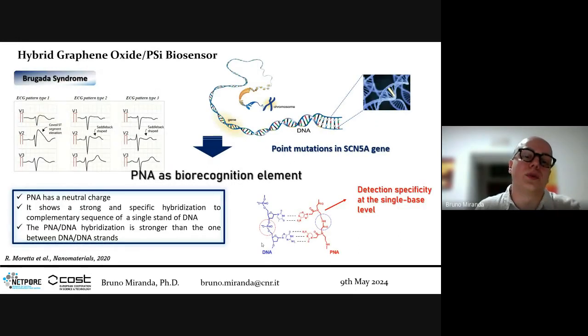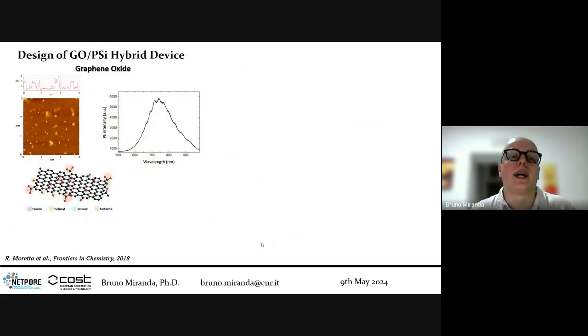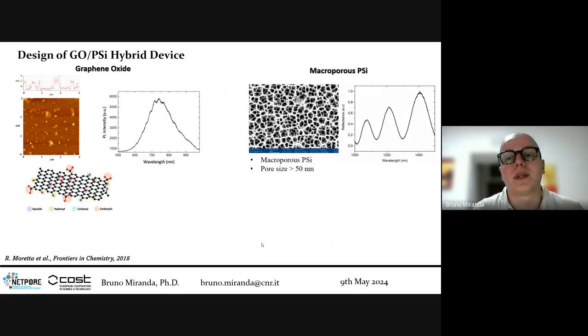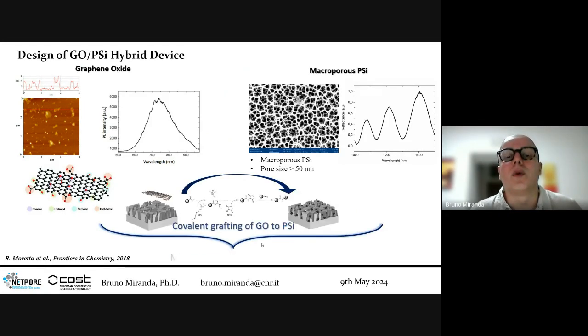How did we plan to do this? We wanted to have a double check, so we wanted to have both photoluminescence and reflectance to monitor the interaction of the PNA on our sensor to immobilize the biorecognition element. We decided to study graphene oxide photoluminescence properties and use macroporous silicon, which is not photoluminescent. We grafted graphene oxide covalently onto porous silicon and obtained a multiparametric hybrid device.